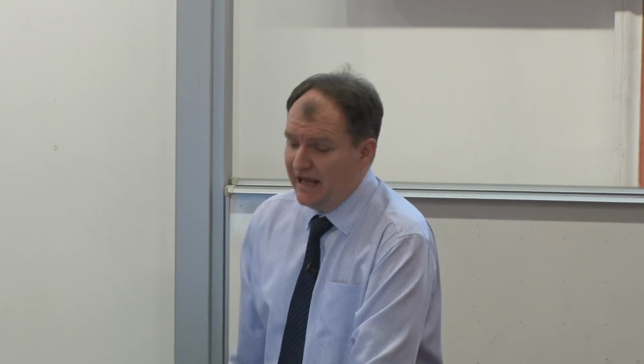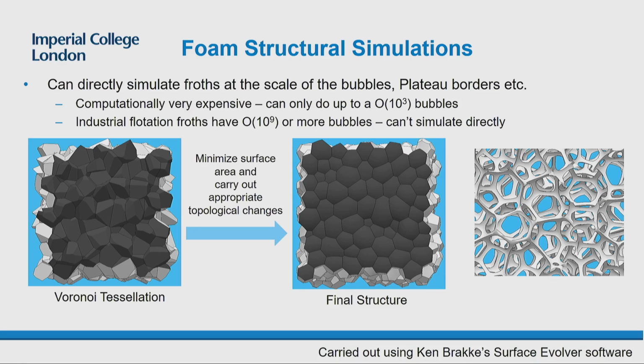The other thing you can do is carry out structural simulations of these systems. I'm not going to go into the details of this, but foams are minimum surface area structures. The main energy in them is a surface energy. They try to minimize their surface energy, and so you end up being able to simulate their structure and shape. The problem with this is, of course, you can only simulate maybe 1,000 bubbles in this sort of detail, whereas a flotation froth might contain 1 billion bubbles. So you're many orders of magnitude off being able to directly simulate a flotation froth this way.